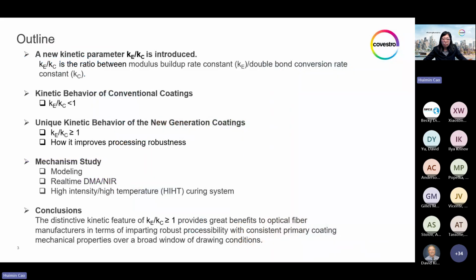We published our first kinetic paper in 2020, introducing a very valuable tool using a draw tower simulator to capture coating cure in a full set of UV doses in order to fit into a reaction kinetic curve. And from those fitted curves, we can obtain the reaction constant for double bond conversion, so-called Kc, C meaning conversion, as well as the modulus buildup reaction constant, Ke, E as in elastic modulus.